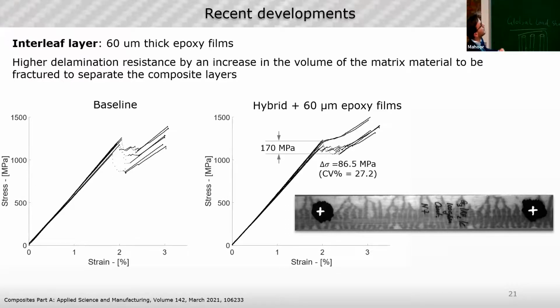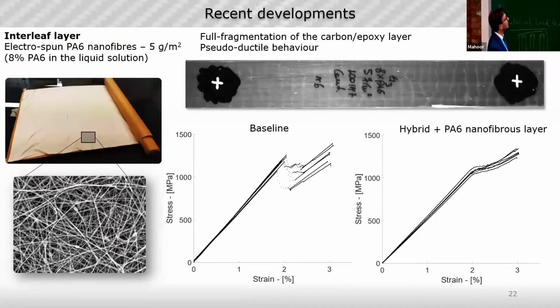And introducing this extra resin and reducing this volume fraction gives us good results, because this is the baseline with a very deep stress drop, because the material was not well designed from the pseudo-ductile point of view. In fact, we have the fracture of the carbon layer, stress drop, and then the final stage. In this case, the epoxy films contributed to reduce the stress drop, but some cases were also borderline. Let's say, in fact, these were borderlines, and a few cases were pure pseudo-ductile. But the outstanding results come from the nanofibers.